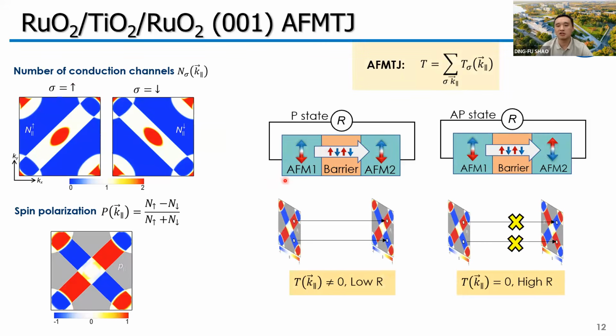So if we use ruthenium oxide as the electrodes to construct the antiferromagnetic tunnel junction, in the parallel state, the conduction channels for the two electrodes will have the same spin polarization. So the tunneling is allowed, we will have a low resistance state. But for the anti-parallel state, the spin polarizations for the conduction channels at the same k-parallel will be opposite. So the tunneling is blocked. We will have a high resistance state. Therefore, we should expect a large TMR.